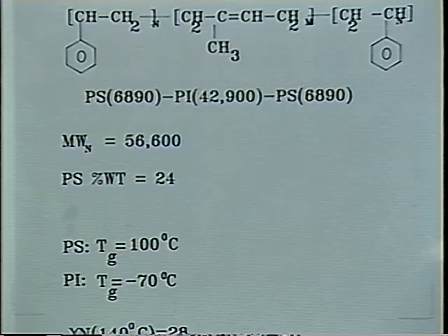Tg is -70. The phase separation is fairly strong in that system, so we cannot say it's weakly phase separated. It is strongly phase separating, but phase separation needs time because of the long molecules needing long times to rearrange into a phase separated structure.